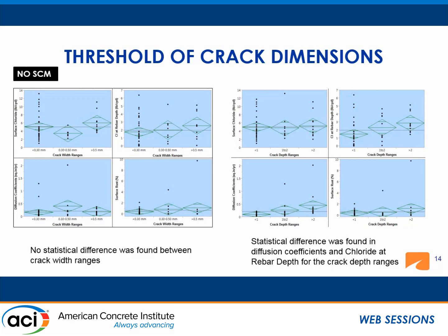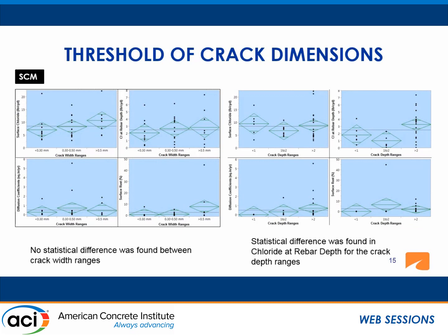These are for the plain cement concrete, and for the plots on the left, the summary is there's no statistical significance at different crack width ranges. While for the crack depths on the right side, a statistical difference was found for diffusion coefficients and the chlorides at rebar depth. And the same analysis was done on the SCM concrete, and exactly the same results were attained, except the chloride at rebar depth was significantly higher for the increased crack depths, while the diffusion coefficients, even though it seems like there's a pattern, was not statistically significant there.